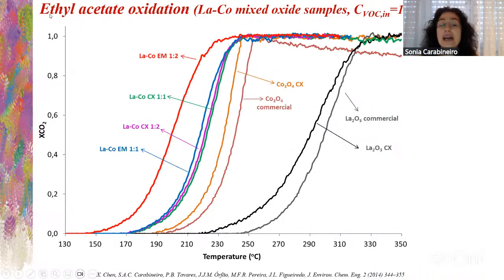So here we have results from ethyl acetate oxidation. It's the same block as before, for lanthanum cobalt mixed oxides. So we have here the commercial lanthanum oxide and commercial cobalt oxide, and prepared with carbon gel, the exotemplated. And here we also have exotemplated mixed oxide samples, and here the evaporation. This is just prepared by evaporation, and this was the best result, 1 to 2 lanthanum to cobalt, so more cobalt than lanthanum. So these were the results.